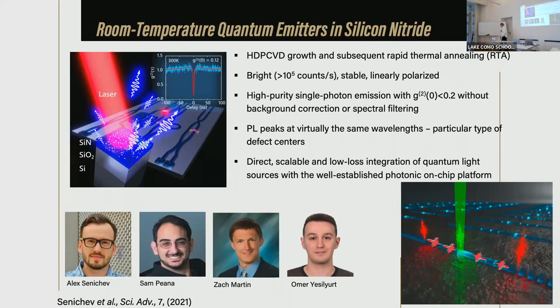It came a little bit like a surprise to us, but sometimes when you work hard for a long time, these surprises do come. So it's well known that in silicon nitride, there's a very strong fluorescence background, and nobody sees any single photon sources. By the way, I'm speaking now about room temperature. So what we did, we used a slightly different way to make this silicon nitride. Specifically, we used high-density plasma CVD. And very importantly, we used very rapid annealing. Later, we could speculate why it's so important, because we don't have full understanding. These results are very fresh, but we have some ideas. And when we do this procedure, you have slightly nitrogen-enriched silicon nitride. So it's not stoichiometric anymore. Nitrogen has a slightly higher proportion.